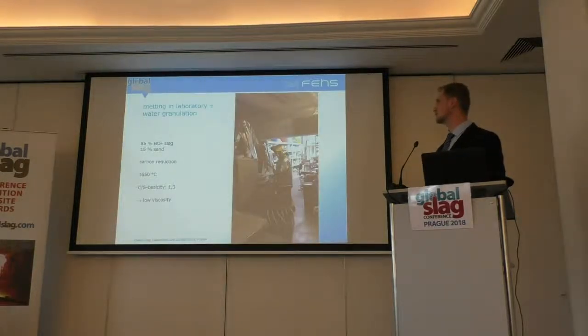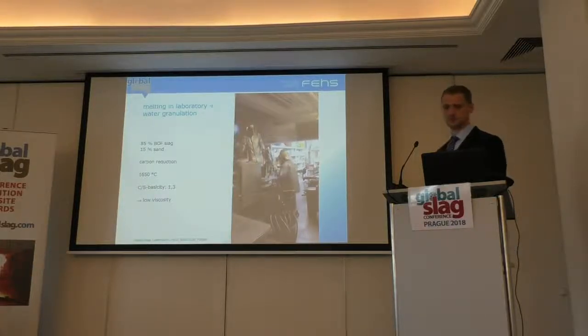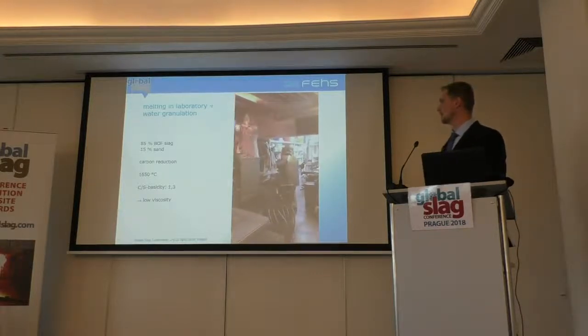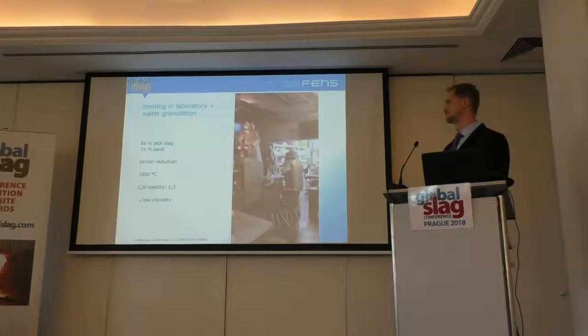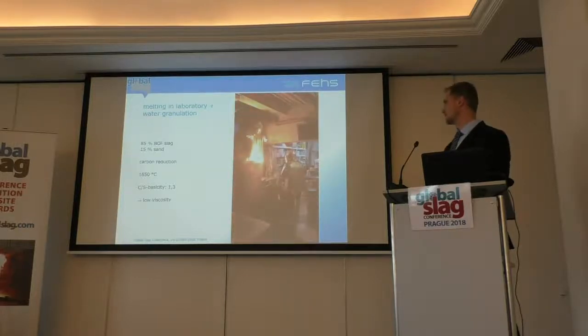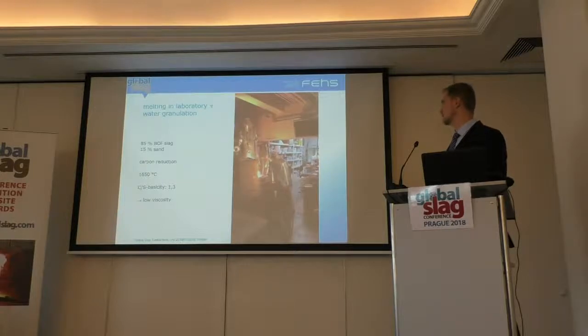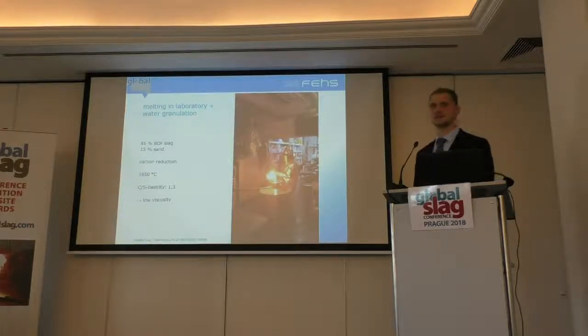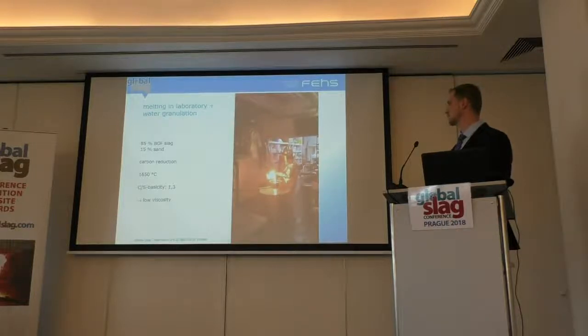Here you see a short video about the water granulation in our laboratory at this basicity. There I put the crucible out of the Tammann furnace. It was a mixture here with 15% sand. So for the viscosity it was enough, as you can see. Here when granulating the slag it's very, very liquid, and that's during a longer time. So I think we needed about 30 seconds to granulate this material. It was not a problem in the viscosity, and we got a very nice material that looks like GBFS.